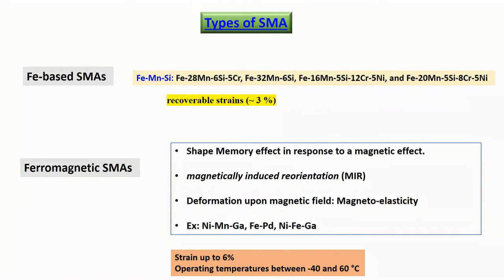That is called the elastic strain. For regular material, metallic systems, this elastic strain is around 0.1% or so. But for the case of shape memory alloy, that is quite high. In case of iron-based one, that is around 3%. Okay, seems high so far, but I will inform about some more materials which are having different recoverable strain.